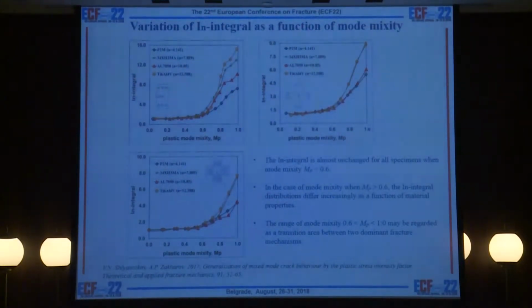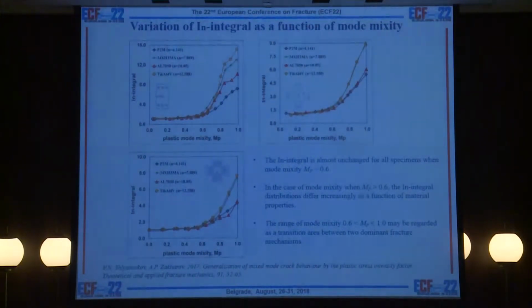In this figure, you can see distributions of the Is-integral as a function of mixed modes and elastic plastic properties of considered materials. I would like to pay attention that the Is-integral is almost unchanged for all considered test specimens when the mode mixity MP is lower than 0.6. In the case of mode mixity MP higher than 0.6, a significant effect of elastic plastic material properties is observed. And this region, when mode mixity MP varied from 0.6 up to unity, may be regarded as a transition area between two dominant mechanisms.